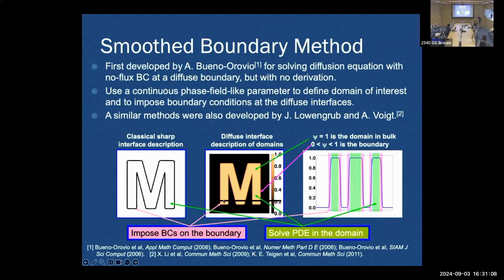As I showed you earlier, the indicator tells you where you want to solve the equation and where you want to set the boundary condition. So this is the M region, a sharp interface, and you say, I want to solve an equation inside the M domain here. I take the cut here, and then the diffuse interface description is this, and I take a cut of this one and plot it. You go from 0 to 1, and where it's 1, I'm going to solve a certain equation. Where it's in between, we are going to set the boundary conditions.